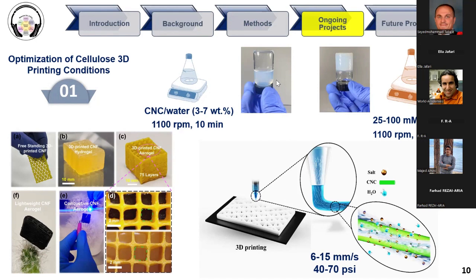So we used different concentrations of salt, because as I mentioned, adding salt is one of the straightforward methods to make a gel and prepare our sample for 3D printing. By using this small amount of salt, we can decrease the Debye length, and we can increase the viscosity of our gel. As we can see here in this slide, whenever we tilt the vial, there is no flow. So this can be a good sign before starting printing. And here we can see the process for my printing. We have extrusion 3D printing, and the pressure that I applied was around 40 to 70 psi, and the speed was 6 to 15 millimeters per second.